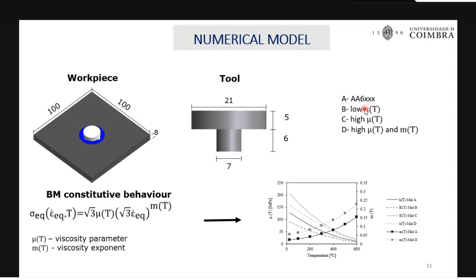In future, it can be related to any grade. For example, if tomorrow you have a new aluminum grade which has this parameter, you can directly relate this result to that material without doing any testing or material parameter prediction. So that is the objective. In another case, I increase the viscosity exponent, and the high viscosity exponent and mu t. Since I am increasing the viscosity, which means I am resisting the flow, if the material has high resistance to flow, it represents that the material has higher strength. So C and D are the higher strength materials. These are the parameters varied and shown here.